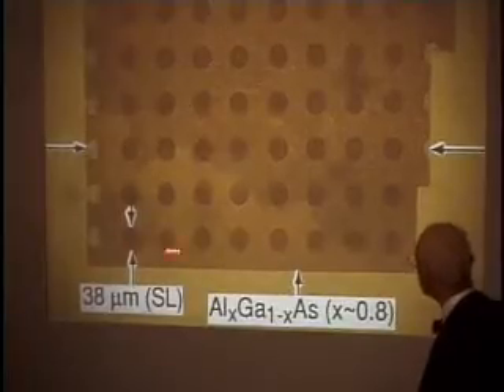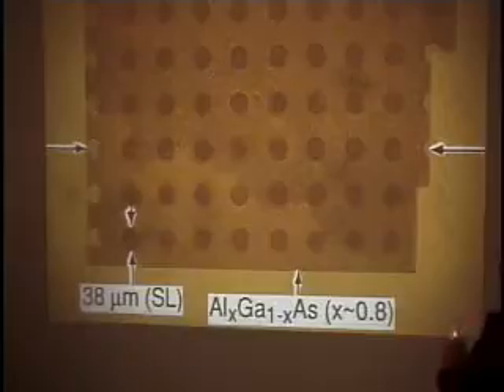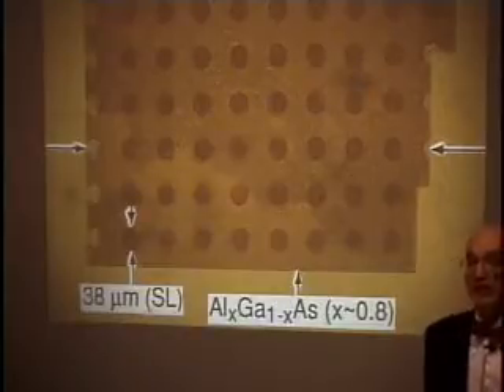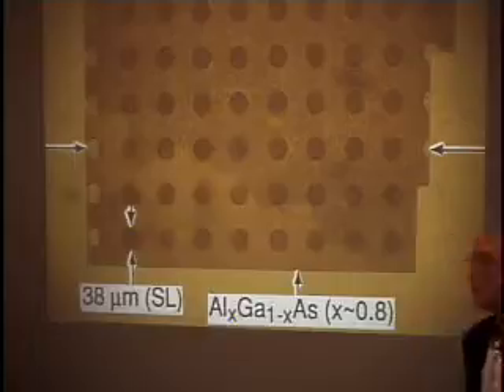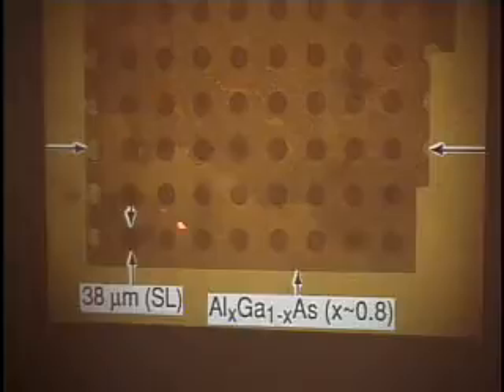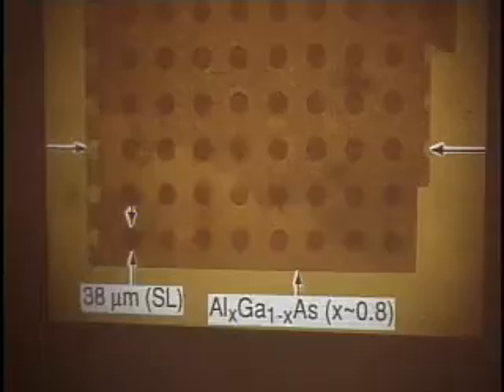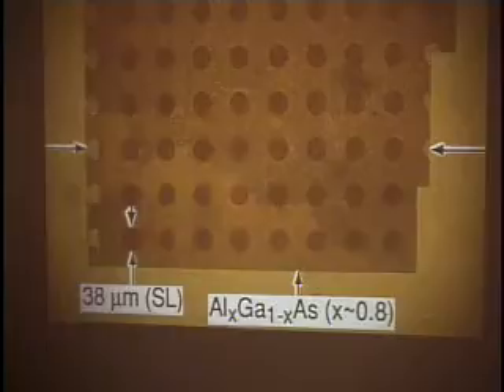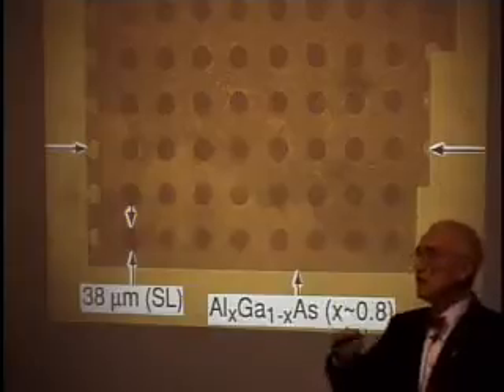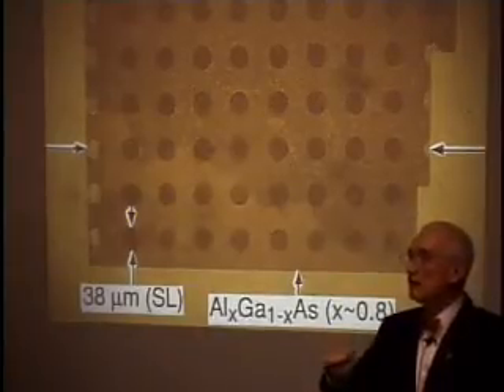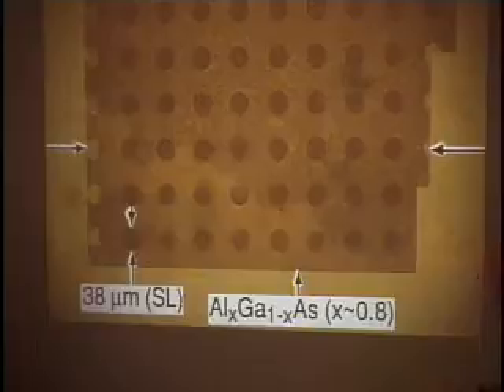Now, sometime later, we put these wafers back into a processing operation, and we put nitrogen gas with some water vapor in it at low temperature, 400 degrees, and something interesting happens. This random alloy, which is about between 70 and 80% composition of aluminum gallium arsenide, does not oxidize very fast. The red dot, which is still superlattice, doesn't oxidize fast because gallium arsenide is a slow oxidizer, and so it's blocking the downward oxidation. So more or less nothing happens here and here.